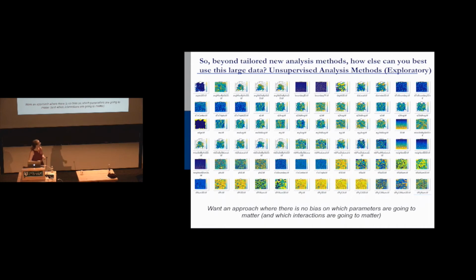And here are some examples. Then we take all of these, and you can imagine we put each value on a slider. So I'm a data point. I have 200 different microstructural parameters, and I have a certain amount of damage at that point. I don't know which of those parameters are important, but I put them each on a slider. Schmid factor is going to be really important. Misorientation is probably going to be important. Grain size might be important.